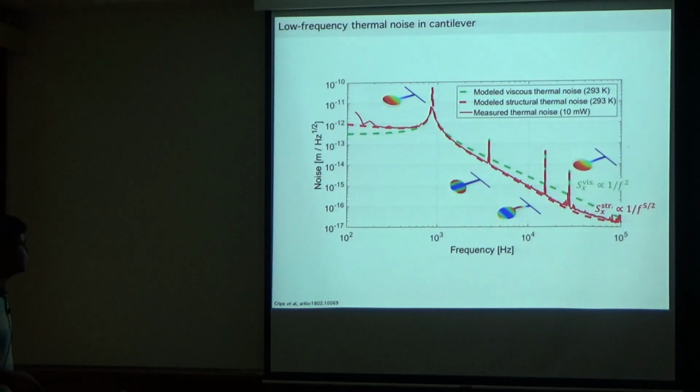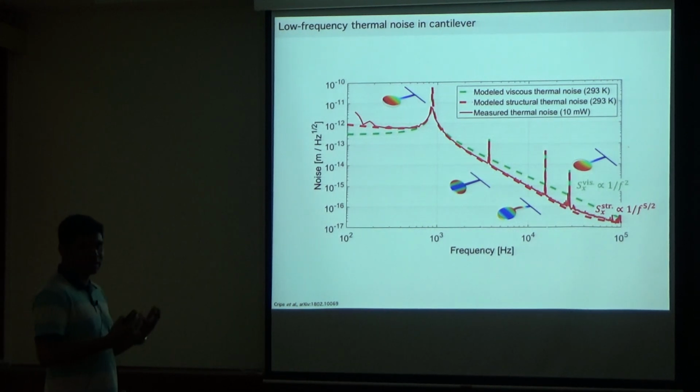And recently we've actually made some interesting measurements which are very close to us having squeezed light from this sort of setup at low frequency. So what you see here is basically the thermal noise measurement of such a device, a broadband thermal noise measurement. And what you would see is that the entire measurement is dominated by thermal noise of the fundamental mode of this end mirror. And one of the interesting things is if you make a broadband measurement such as this, you would actually start seeing differences between the various damping mechanisms that happen in such a cantilever.